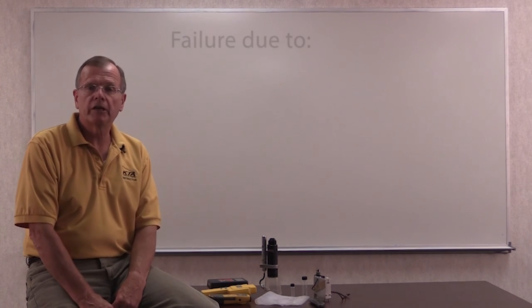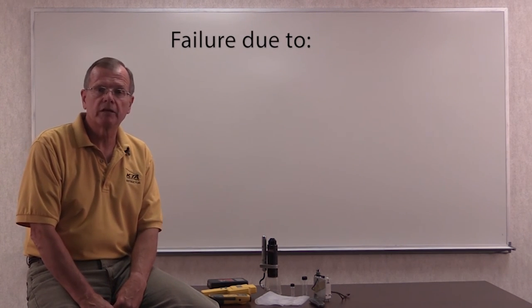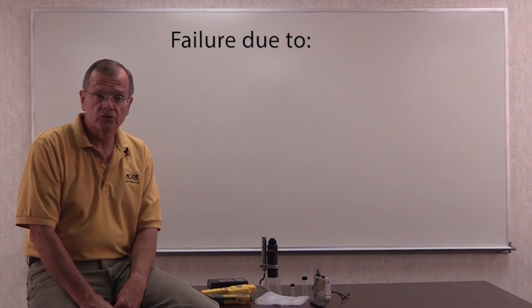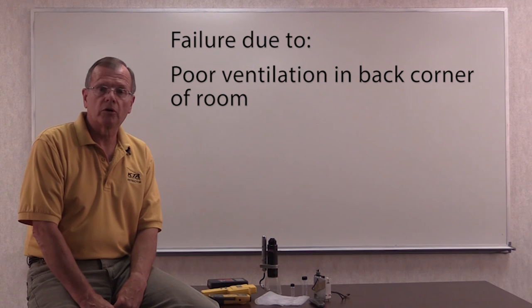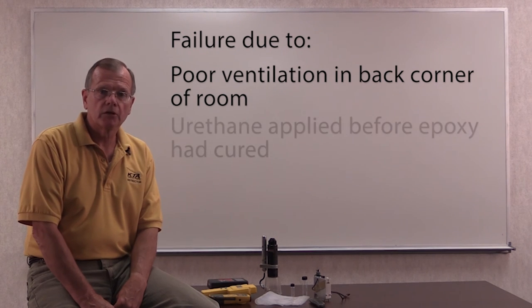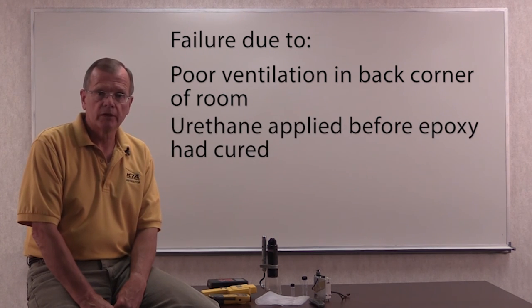In summary, the failure was the combination of two application-related problems. The first, the failure in the corners due to poor ventilation that retarded the cure of the epoxy. The urethane was applied before the epoxy had cured, entrapping solvents and creating a weak plane at the top surface of the beige epoxy.